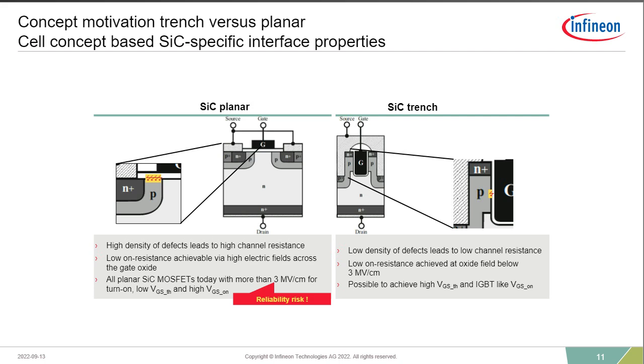Because of the number of defects in the c-plane of silicon carbide, or the horizontal plane, you have to have a relatively large cell structure for a planar device in order to ensure the same RDS(on) specification. Take, for example, these two devices we show here, the trench gate cell and the DMOS cell. You can see a clear difference in the size of those devices, and that's because of this particular P region, and having to have enough surface area in that region to assure a proper defect density.